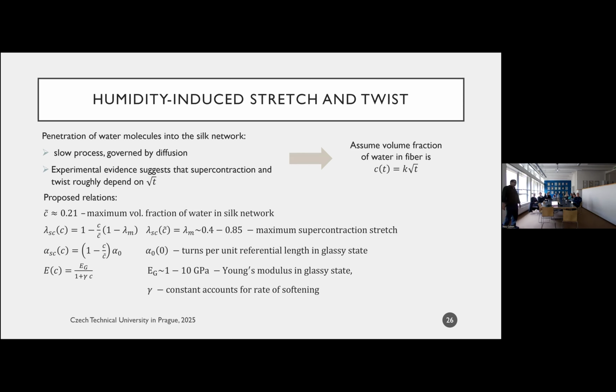And so the whole process itself is governed by diffusion. If it's governed by diffusion, the amount of water that I have in the silk network should scale as the square root of t, give or take, right? So the experiments actually support the square root of t. This is kind of a hallmark of diffusion. And so the K here accounts for the diffusion coefficient, the geometry, and all of the diffusion related parameters.